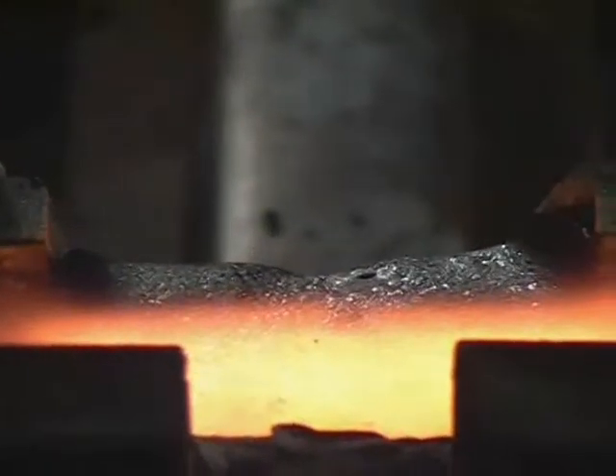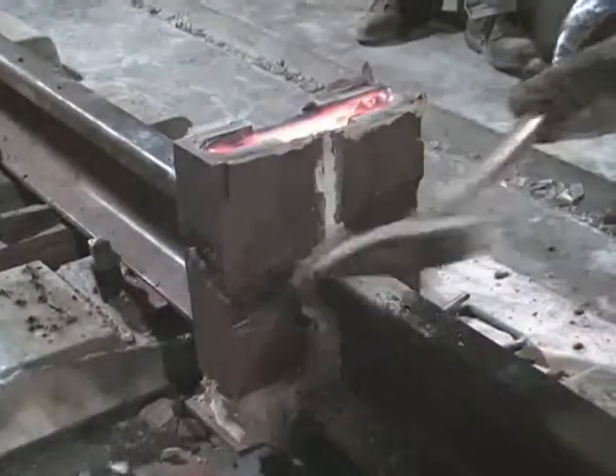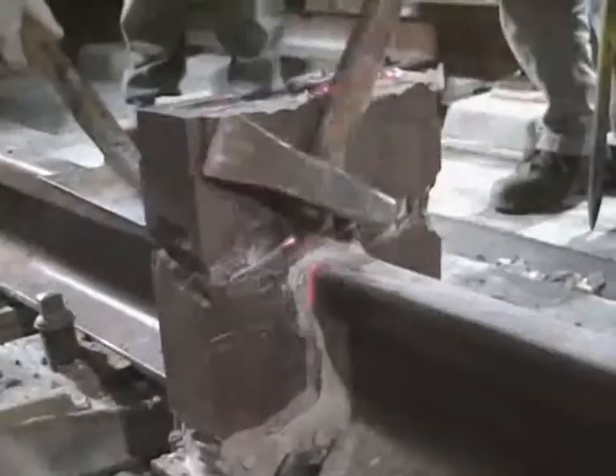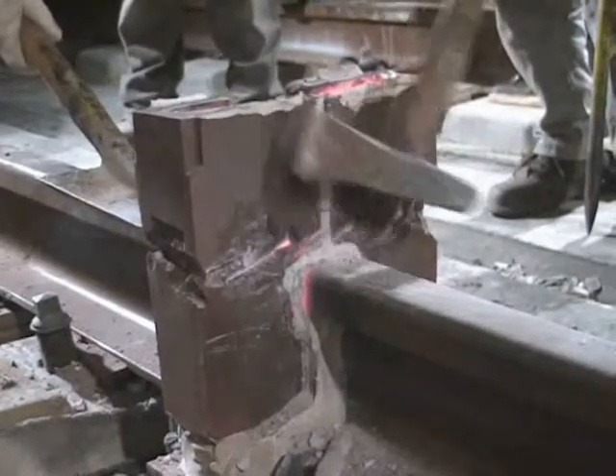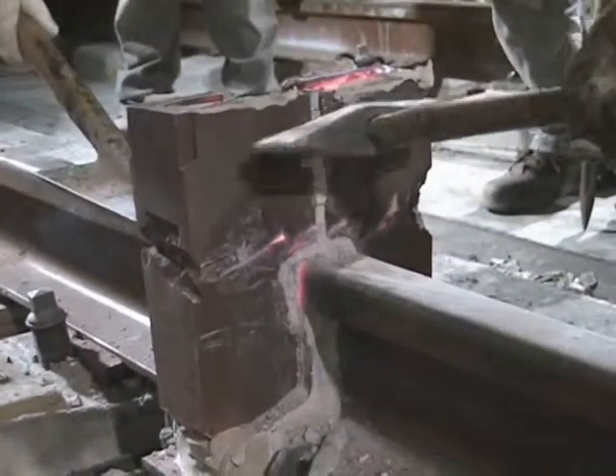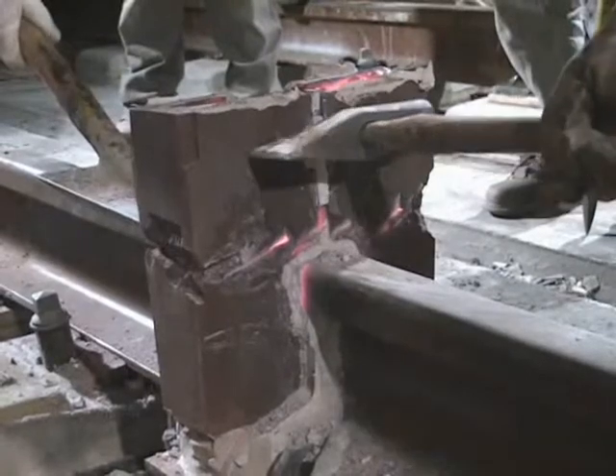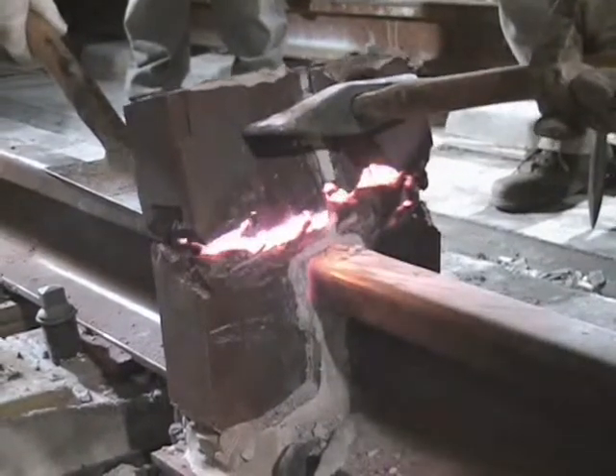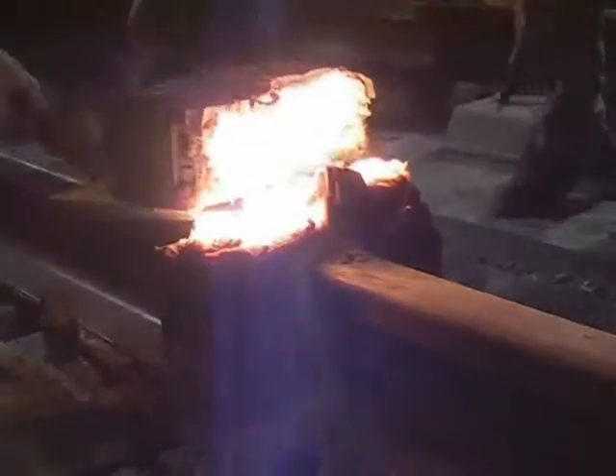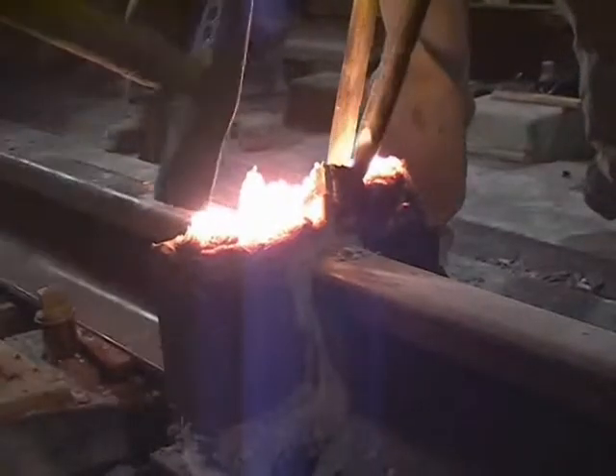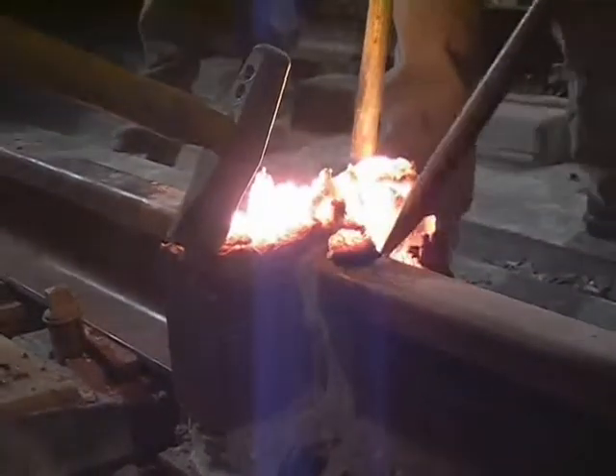After a few minutes cooling time, the mould is broken away, exposing the glowing orange metal inside. Again, the timing must be accurate. If the mould is opened prematurely, the liquid metal will flow out. Too long, and the metal will have begun to harden, making the job of shearing and trimming the weld extremely hard.